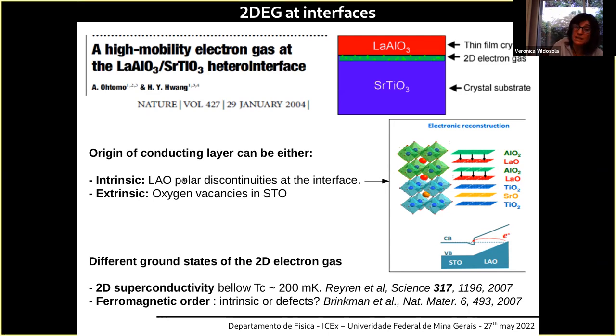And the origin can be intrinsic in this system, because lanthanum aluminate, in the 001 direction in which it is built, is a polar material, yes? It develops an electrical polarization that grows with the width of the layer. So after a critical width, the polarization is so large that the system itself has to screen it and send some electrons to the interface. And that is one of the intrinsic mechanisms to generate these 2D metallic states at the interface.